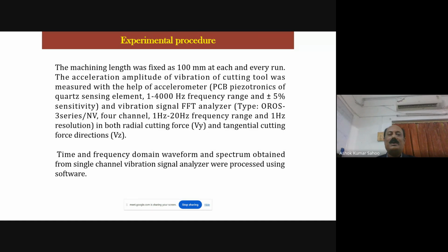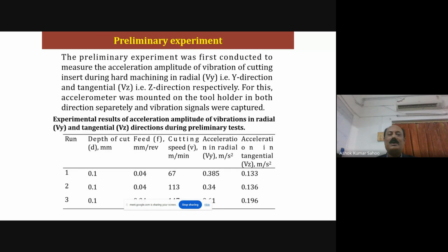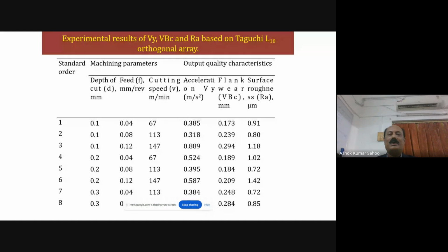The acceleration amplitude of vibration has been measured through the accelerometer and vibration signal FFT analyzer in both the radial cutting force and tangential cutting force direction. That means we measure the acceleration amplitude of vibration in the radial direction, that is Vy, and in the tangential direction, that is Vz. Time and frequency domain waveform and spectrum obtained from the single channel vibration signal analyzer were processed through the software. So these are the readings obtained. As we observe here, the acceleration amplitude of vibration is maximum in the radial direction. This is due to the higher thrust component force in hard machining conditions as compared to the tangential direction. That's why in further hard machining operations, we measure the acceleration amplitude of vibration only in the radial direction.